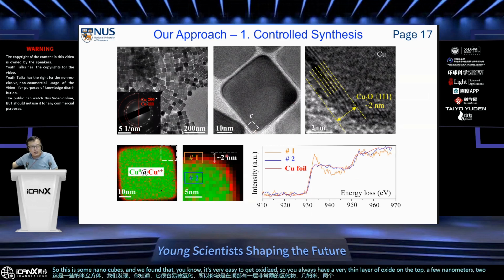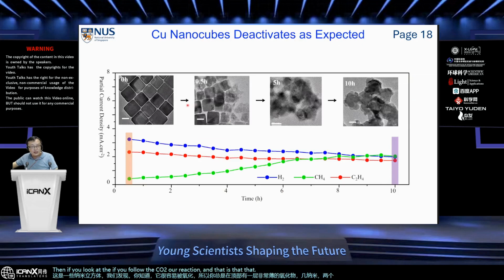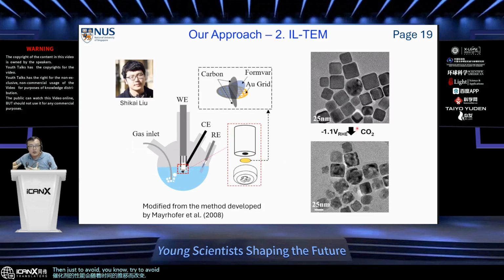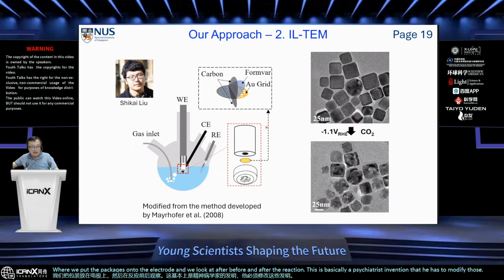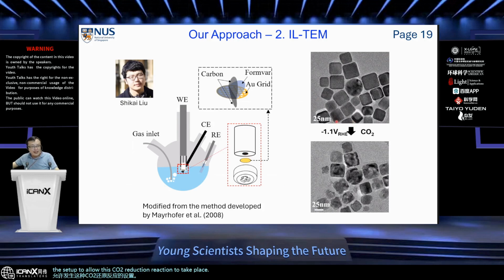Then if you follow the CO2R reaction, that process sort of follows the reported trend, right? You have the particle, then you don't have it anymore, and the performance of the catalyst does change with time. So this is consistent. Then, just to avoid the observation bias, we try to follow the same particle before and after the reaction. Instead of using in situ liquid cell TEM, which limits your resolution because of the liquid, we use this identical location setup where we put the catalyst onto the electrode and we look before and after the reaction. And this is basically Shikai's invention, that he modified the setup to allow the CO2 reduction reaction to take place. And the findings are very interesting.